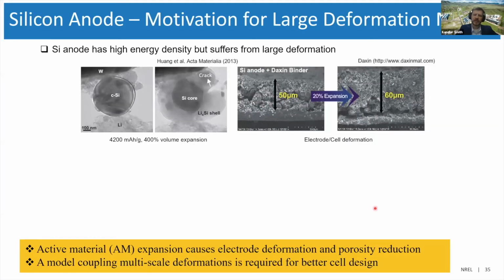So first, going into the large deformation model, I think you're probably all familiar with silicon. Big problem is that you've got large capacity, that's great, but up to 400% volume expansion between a full charge and discharge cycle. And so over many cycles, it forms cracks in the material. Also, the SEI layer can be fractured and reform and thickens over time.